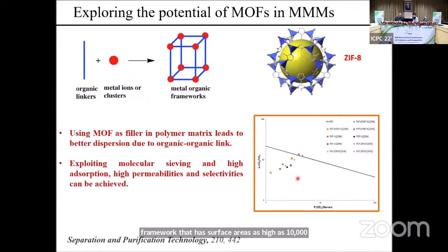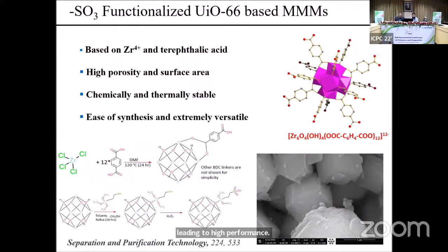Already in the literature, these metal organic framework based membranes have shown potential even beyond the upper bound. So MOFs are the way forward because they comprise these organic linkers. Because of their organic linkers, there is a better compatibility with the polymer matrix, leading to high performance mixed matrix membranes. At Composites, we have carried out several studies using these metal organic frameworks. I will go through a few to give an idea of how these MOFs are behaving and what their performance is.